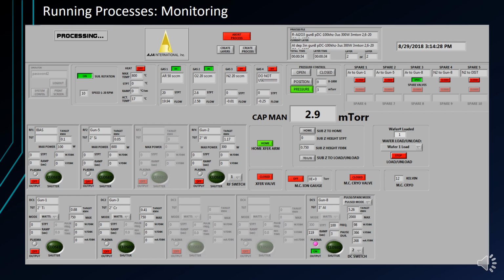This is a snapshot of a reactive sputtering process for aluminum oxide. We can see that the process is currently in the second of 2 layers for the process. The rotation is set to 10 RPMs, argon flow is on and set to 20 SCCM, oxygen flow is on and set to 2.6 SCCM. The pressure is set to 3 millitorr and holding at 2.9.